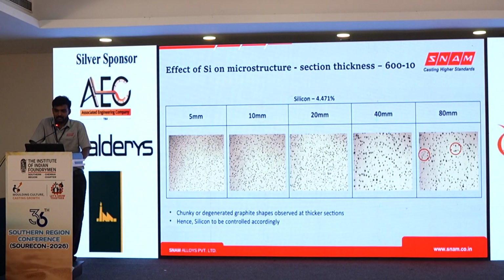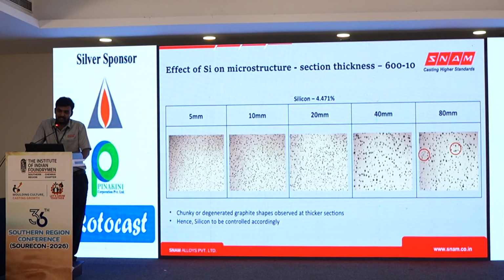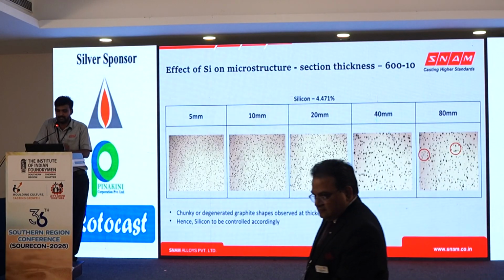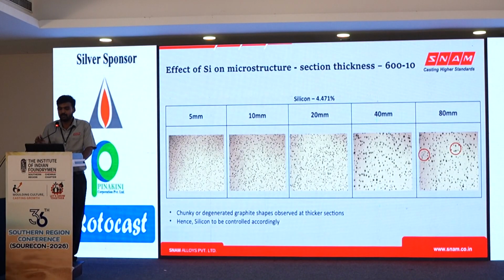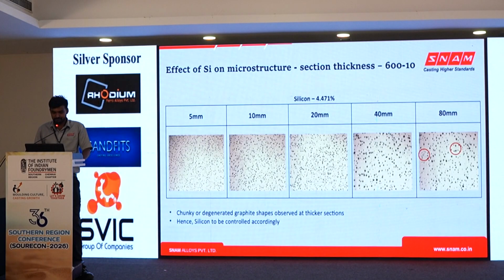Effect of silicon on microstructure. Here, with the silicon percentage at 4.4, we can see the microstructure of different cross-section thicknesses: 5 mm, 10 mm, 20 mm, 40 mm, 80 mm. In a thicker section we can see the start of the formation of chunky graphite or degenerated graphite, so we should control silicon within about 4.3.